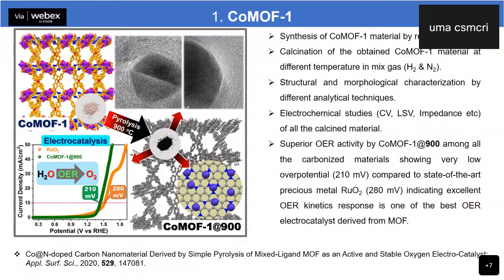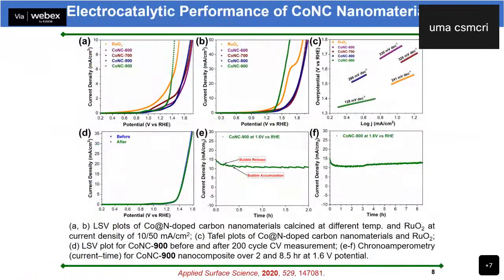In the case of OER, we found that the cobalt 900 material, meaning the material calcined at 900 degrees Celsius, has good electrochemical activity. 210 millivolt overpotential is required to achieve the 10 milliampere current density. So we can say the cobalt 900 material has good activity as compared to cobalt 600, 700, 800. Then, to see the electrochemical kinetic activity, the Tafel slope was calculated from cyclic voltammetry, and in the case of cobalt 900, the Tafel slope value was 128 millivolt per decade. So it has a lesser value as compared to the others.